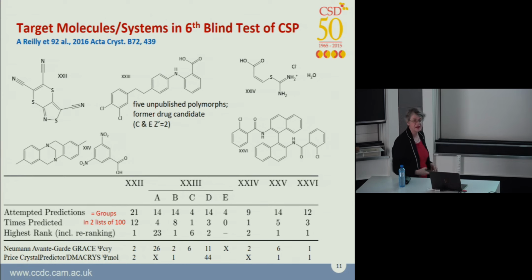The next line is the number of successful predictions, and each group could submit 2 lists of 100 crystal structures, and that's the number that contains the one that was successful within that list. The next line is the highest rank, including the re-ranking. So first means that someone got it as the most stable of all the crystal structures they generated. You can see that the small rigid molecule did rather better than the 3-component system or the co-crystal with 2 molecules or this very flexible molecule.